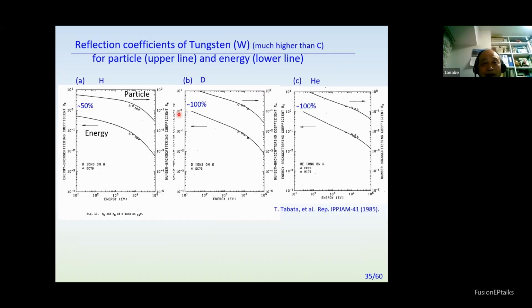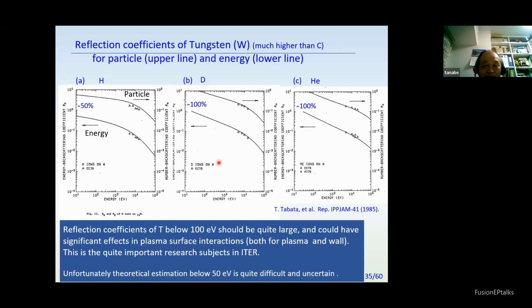If you go to tungsten, the reflection coefficient becomes very high—the heavier the material, the higher the reflection coefficient. In the case of tritium, since there is no data, most of it should be based on theoretical estimation.